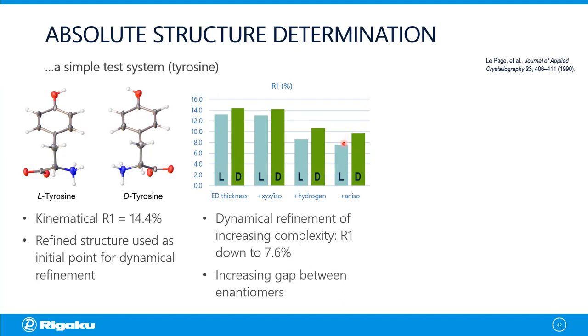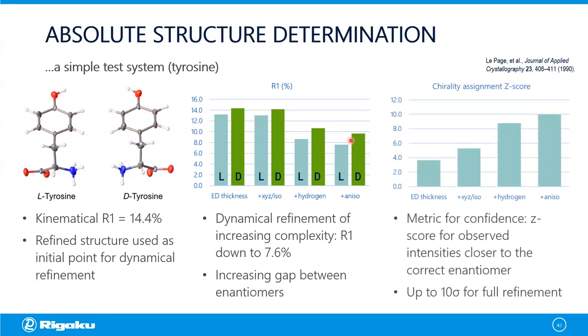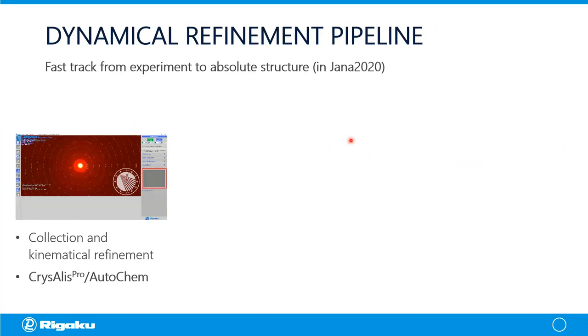And we see that the gap between the enantiomers also drops, giving us better satisfaction that we have, in fact, gotten the correct chirality. And so Klar et al. used a Z score in order to provide a metric for confidence here. And what we find is that for this particular sample, we have quite a high Z score, on the order of 14, if I remember.